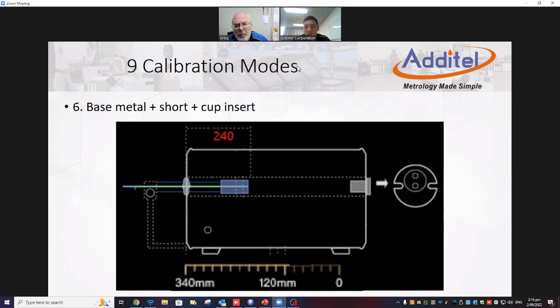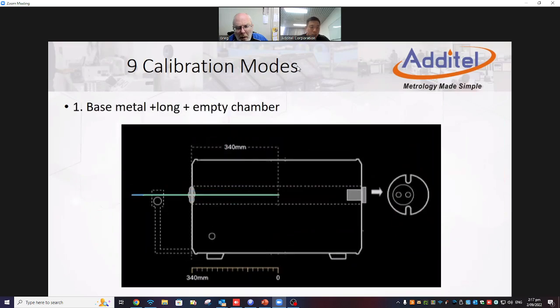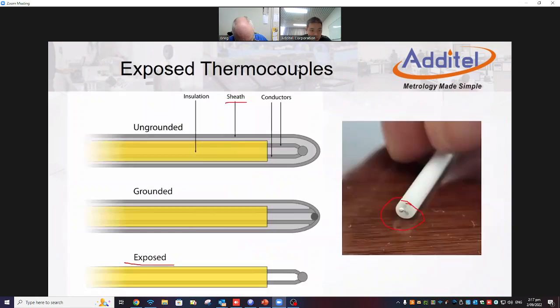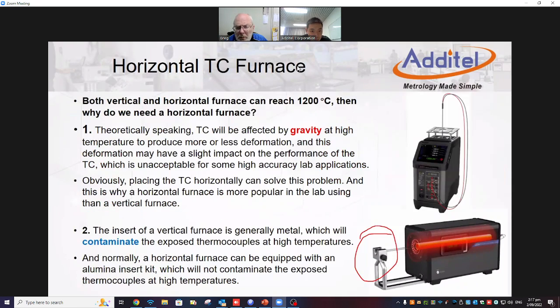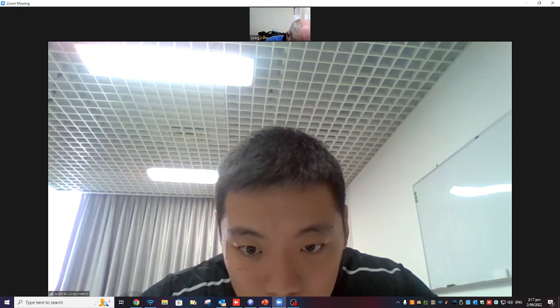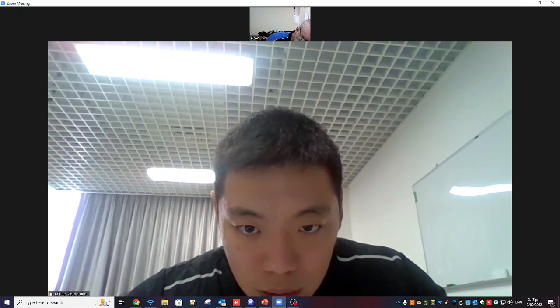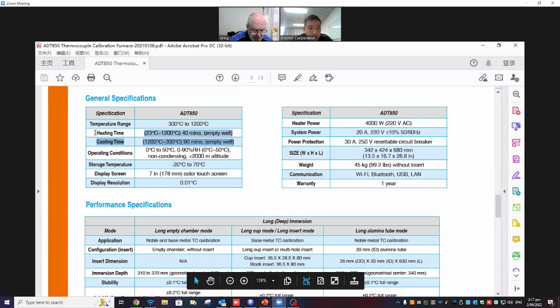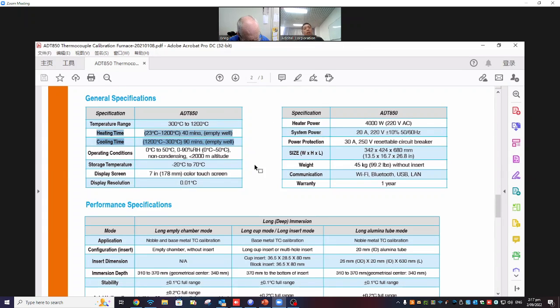What is the heating time from ambient to 1200? Let me check the data sheet real quick. Yeah, the heating time would be 40 minutes from room temperature to 1200. Cooling time would be 90 minutes from 1200 to 300 degrees Celsius. The temperature range of the furnace is from 300 to 1200.